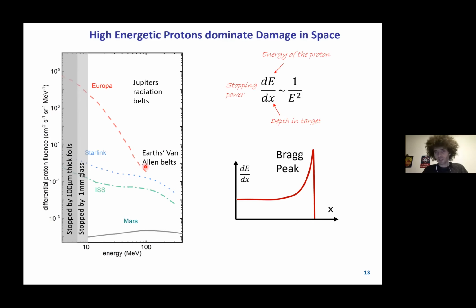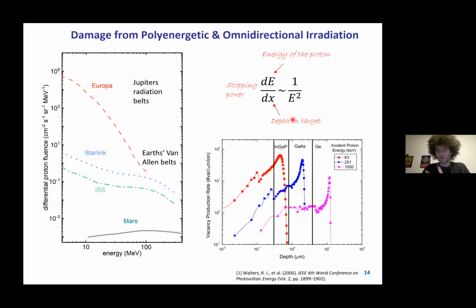So the stopping of high energy protons is a function of their energy, and the stopping power, dE over dx, scales with 1 over E squared, meaning that lower energy protons will be stopped faster. And this allows you basically to block very low energy protons quite efficiently already by 100 micrometer thick foils or 1 millimeter glass. For tandems, this is now also quite important because a certain proton energy would only damage one subcell in a tandem or in a triple junction.